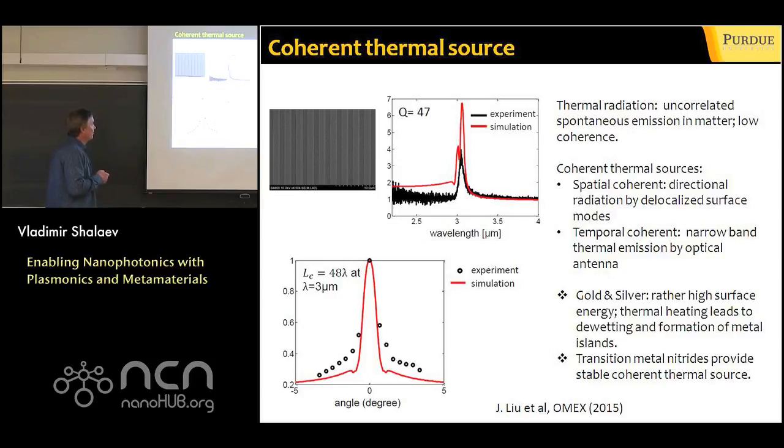In terms of frequency domain, you could see that it's a very sharp radiation actually. In this case, it was designed to center around 3 micron. So you see how dramatically you could modify the thermal radiation. You heat it up, and instead of having this broadband radiation, you have thermal radiation which is peaked around 3 micron. And that occurs because you excite these antennas made of plasmonic materials. They resonate at 3 micron and you have this peak in emission.